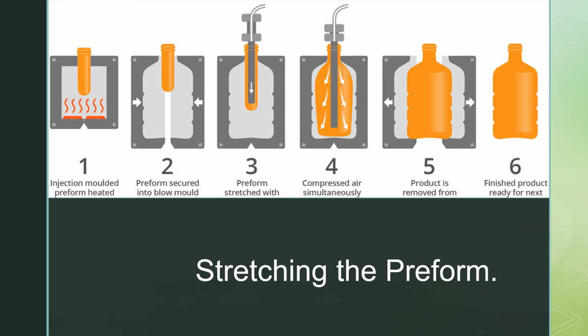The inside of this mold is shaped exactly like the finished bottle. Inside, a long needle pushes up through the preform, which is suspended with the screw end facing downward. The needle stretches the preform upward towards the top of the mold, which will be the bottom of the bottle, and simultaneously blasts enough pressurized air into the preform to force it against the sides of the mold. The blow molding process must happen quickly in order to maintain the bottle's integrity and consistent shape.